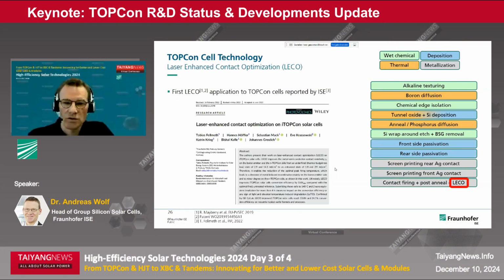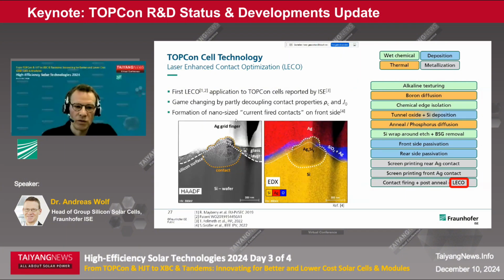Finally, LECO was a hot topic in this conference already, and we agree fully that this has been a breaking innovation in the TOPCon process. We at ISE were one of the first to apply this process to TOPCon cells, and it was game-changing because it decoupled the contact resistance from the contact recombination parameters because of the formation of these very small current-fired contacts.